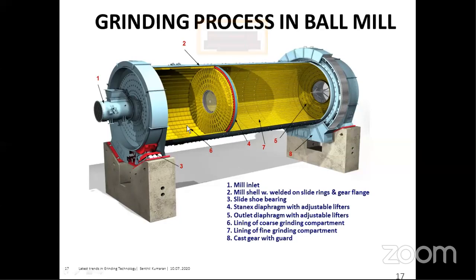For this first compartment, since it's a bigger size media, the impact will be more. For protecting this, bigger size stepped liners were installed. In the second compartment, where the impact is lower, corrugated liners were placed. When the media directly hits the liners, the damage, wear and breakage will be higher, and we don't want that to happen at the third point. That's how the percentage of the critical speed is chosen.